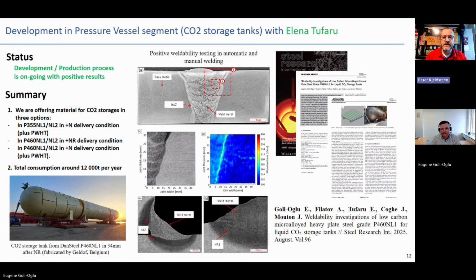Yeah. What is it in the steel that enables it to still be tough at minus 50? It's a combination, I would say, between chemical composition and technology. But in general, the lower the carbon, the better the toughness. The lower the sulfur and phosphorus, the better the toughness, because then the purity of the steel is much better. But there are also extra points like microalloying of the steel, by niobium, vanadium, titanium in combination or in single way, which also give you extra values of low temperature toughness.